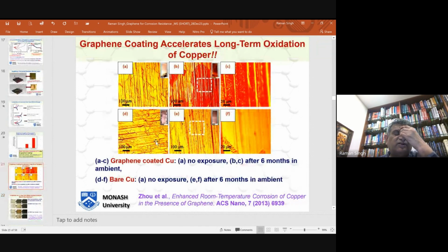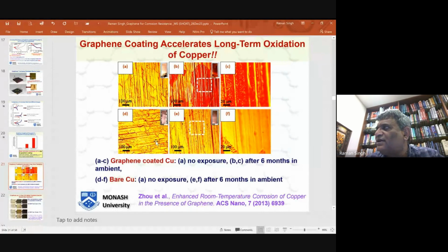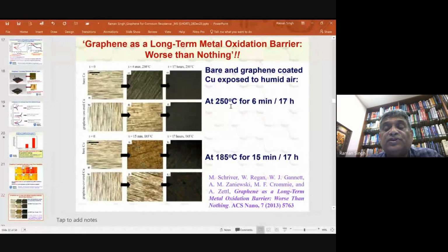When we were showing this kind of varied results, that we are getting improvement by 2 orders of magnitude and someone was not getting much improvement at all, in the middle of that, we got a paper which says graphene coating, as a matter of fact, accelerates corrosion. We were talking about improvement in corrosion resistance. This paper, published in a very reputable journal, says that it accelerates corrosion. As if one was not sufficient, another group says, see the title of the paper, graphene as a long-term metal oxidation barrier, worse than nothing. Means if you don't have coating, it will be performing better. It will be giving you better corrosion resistance.